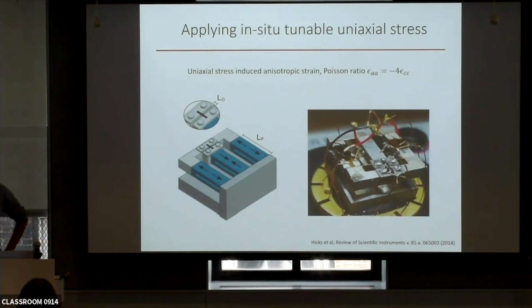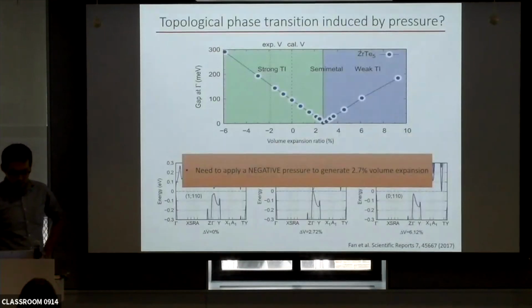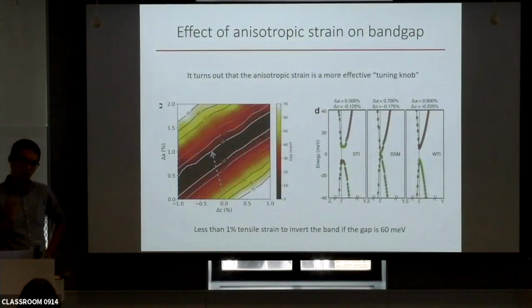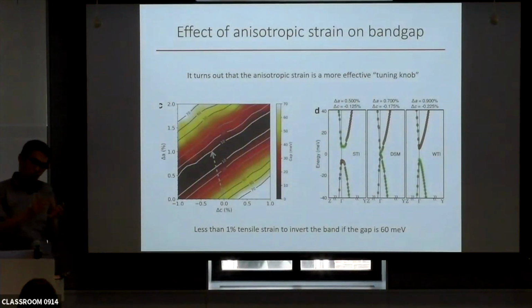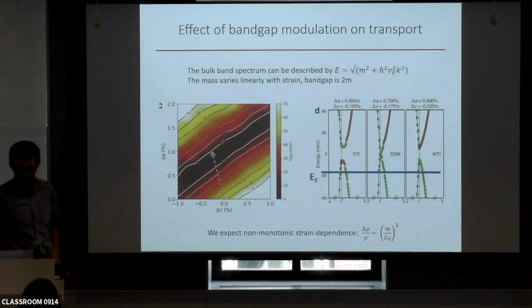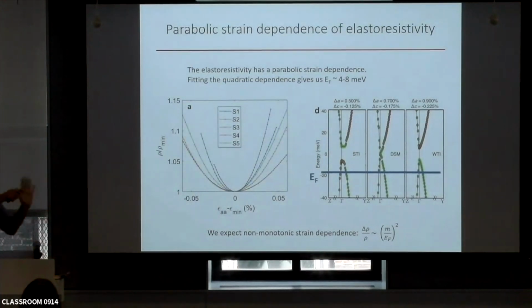And maybe a second question, in terms of your interpretation of the band gap closing, is there also a role of the symmetry breaking strain versus the isovolume strain? Does that matter? This is actually not a symmetry breaking strain, because the crystal is orthorhombic. When we apply this anisotropic strain, it is still A1g. So that's why this nonlinear elastic response is very striking, because you shouldn't expect any nonlinear response. Okay, I missed that. Okay, cool.